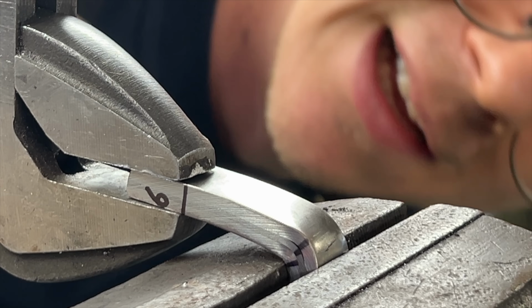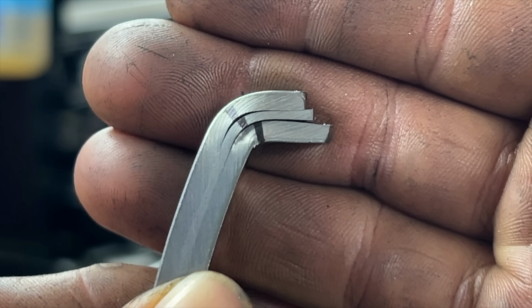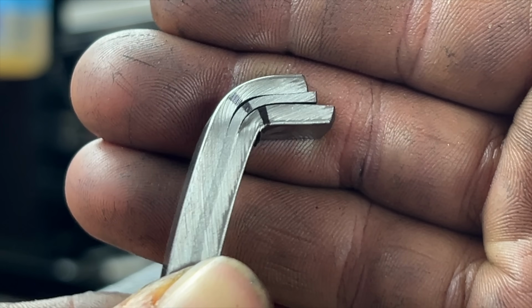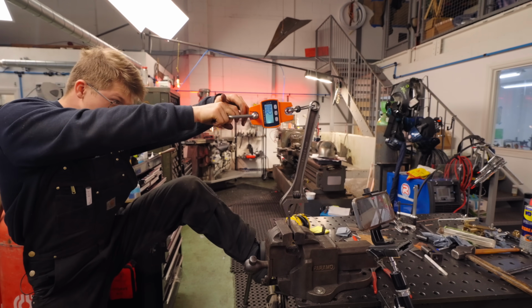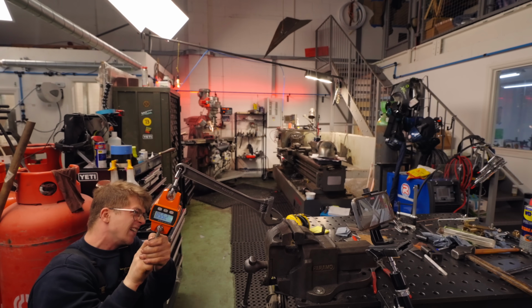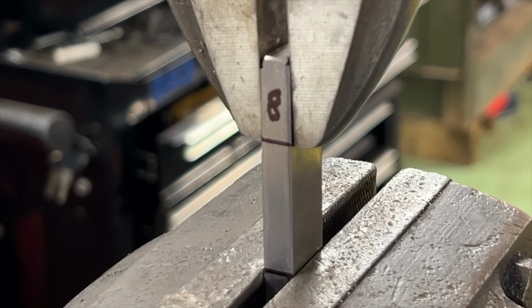Yep. Did not like it. Looks like the zirconium stuck to the titanium, but the zirconium did not stick to the steel. 7, niobium. Oh, that's good. Very promising. Titanium control, 8.